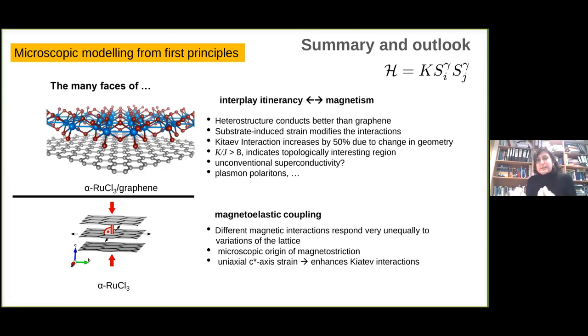could show to you that alpha-ruthenium trichloride on graphene has many phases, and one expects, in fact, in this system, many possible new phases. So on the one hand, we have the increase in conduction in graphene due to the doping, the hole doping, also due to the strain induced on the ruthenium trichloride. We are changing drastically the interactions in the system, and our prediction is that we bring the system more near to the Kitaev limit.